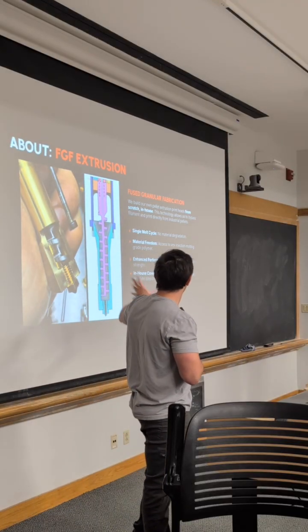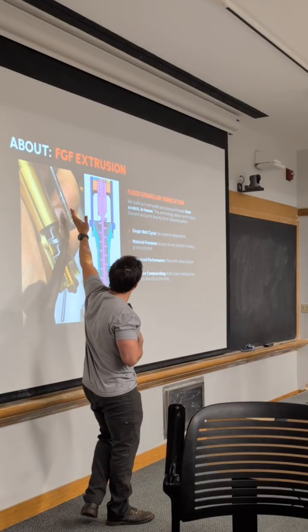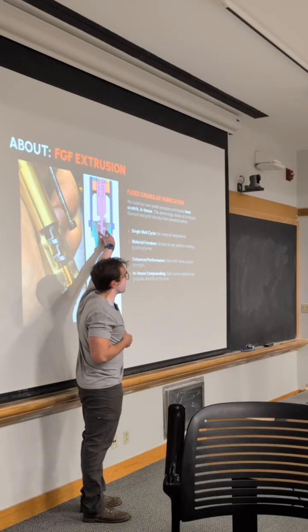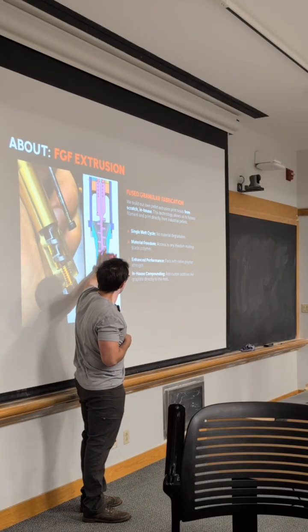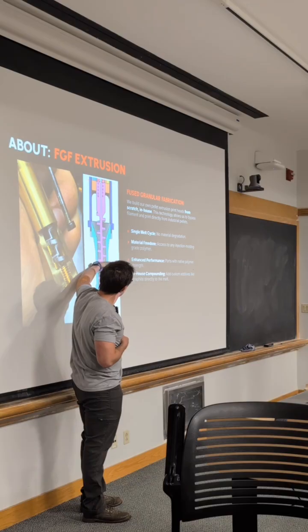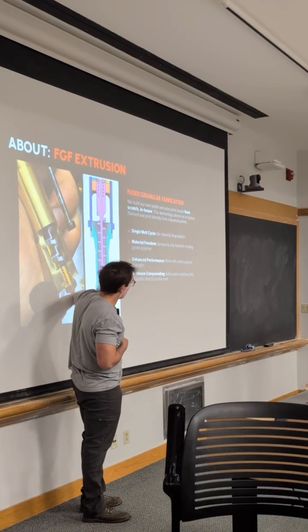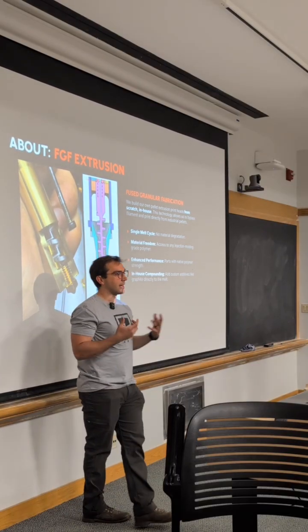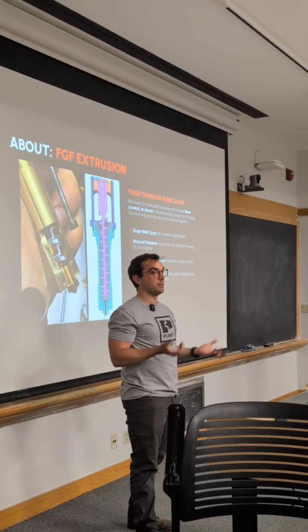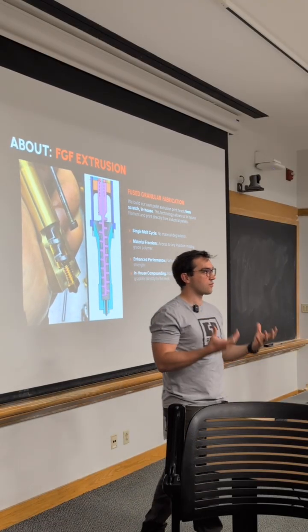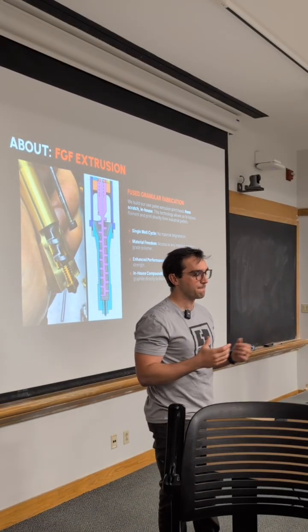And again, you can see kind of how the pellets would come into this barrel. They would be captured by those flutes of the screw and be dragged down. And the hot zone is roughly from here downward. There's a thermal gradient here. And that allows the material to be compressed, heated, and then extruded reliably inside of the print head.